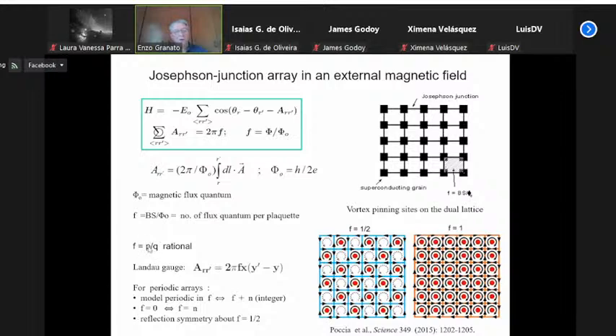So if f is a rational number, p divided by q, you can show using a Landau gauge, in which the vector potential is, let's say, 0 in the x direction and non-zero in the y direction, that the vector potential depends on the distance in the x direction, and the line integral is 2 pi times f. Therefore, if f is an integer, then you see that this quantity here is just a multiple of 2 pi. And if it's a multiple of 2 pi, inside the cosine it makes no difference. So when f is an integer, this system behaves as if it has no magnetic field at all.